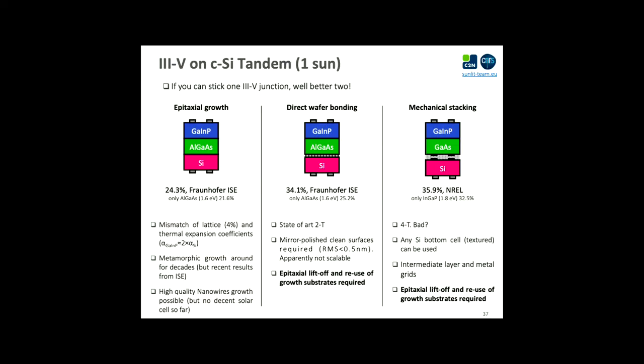Another possible approach is to grow, instead of a 2D layer on top of the silicon, in the shape of nanowires. And since these nanowires are relatively, I don't know, 100, 150 nanometers in diameter, they can relax the stress on the side wall, and so you can grow single crystal, very high quality III-V materials or junctions on top of the silicon bottom cell. So at the moment, there's nothing fundamentally wrong with this approach. The problem is to have good efficiency, and at the moment it is still relatively limited.